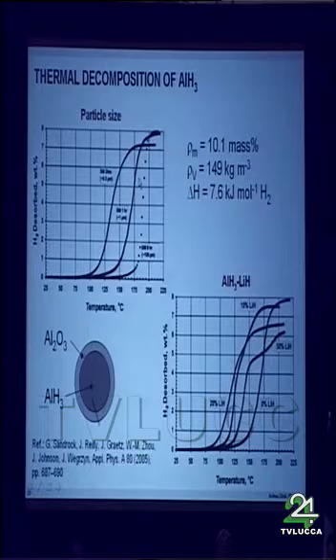Now, the next very interesting system is aluminum hydride. That was investigated also recently by Gary Sandrock and co-workers. And the first observation was that the kinetics of the hydrogen desorption is very much particle size dependent. So the smaller the particle size, the faster the desorption. This is not really very surprising. And then aluminum hydride was combined with lithium hydride, and this also lowered the desorption temperature. And the desorption temperature, as you can see in this figure, is somewhere between 100 and 150 degrees centigrade. So in an interesting range.